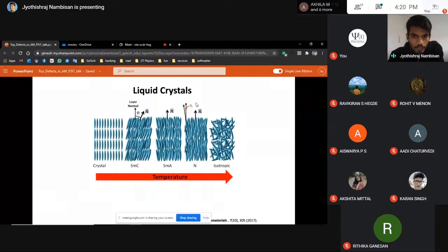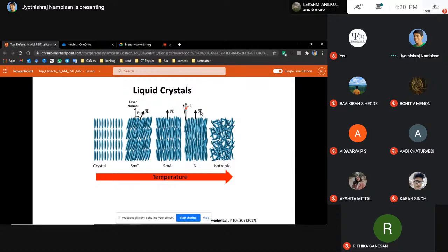So there is some sort of an orientational order, but there is no positional order. If you translate this phase by some amount in any direction, it looks the same. But if you change the orientation with respect to this axis, which is known as the nematic director, which is one of the principal axes, there is actually a difference in the system.